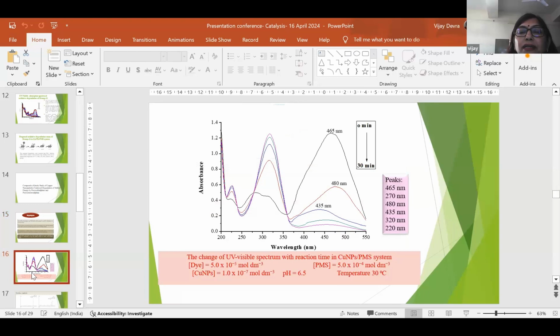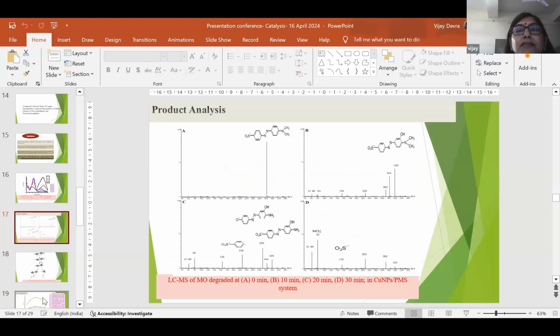system. The UV peak at 465 lambda max degraded within 30 minutes, which confirms that methyl orange degraded in the copper nanoparticle peroxomonosulfate system, which is also confirmed by the LCMS results. Here we show that as time passes, at 0 minutes this indicates the methyl orange structure. After 10 minutes, it degraded into another intermediate, and finally converted into less harmful products such as nitrite and sulfite.